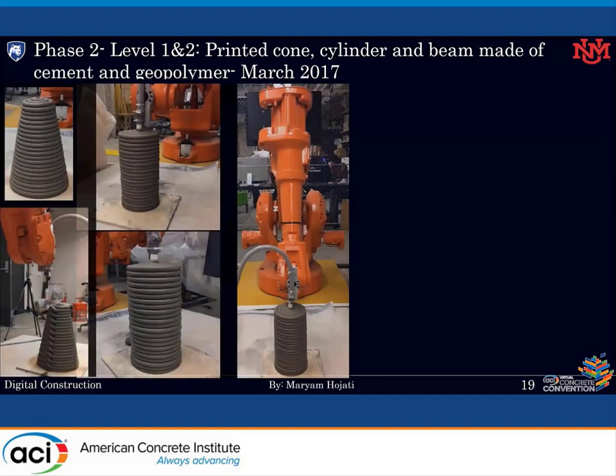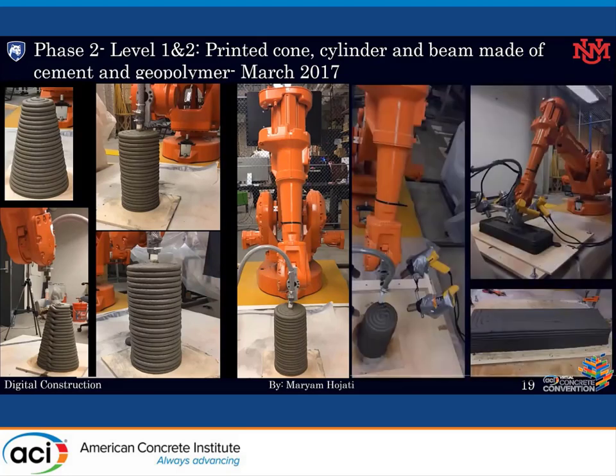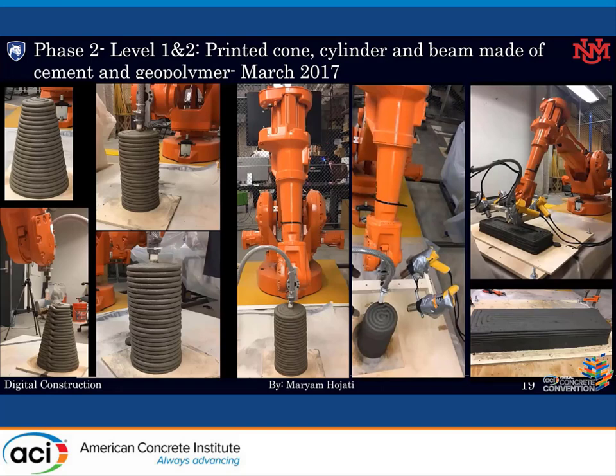At the initial step, we spent quite good time to adapt our material and system for 3D printing. We designed different materials with different rheological characteristics. Additionally, we played with different parameters in the printing system, such as printing speed, size of nozzle, power of pump, and design of different types of toolpaths to be able to successfully 3D print cone, cylinder, and beam for level 1 and 2 of phase 2 NASA project.